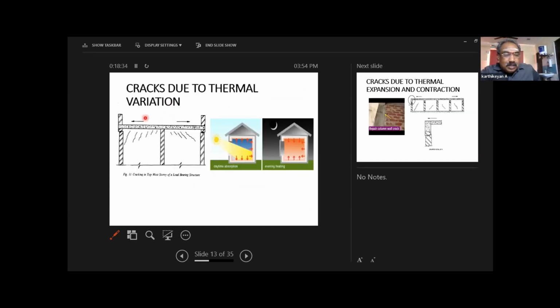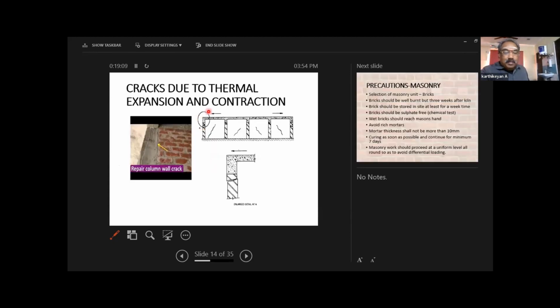Due to thermal variations, in our country, in Tamil Nadu, in South India, our temperature in summer is 45 degrees Celsius. In winter it is 20 or 25 degrees Celsius. So a 20-25 degrees Celsius variation is there. The top surface expands. When the top surface expands, there are cracks at the slab and wall junction. People may think if you provide a beam, there will again be less chance of cracks. Yes, if you provide a proper beam, there is less chance of cracks. But my next slide shows that even if you provide a beam, there is a chance of cracks below the beam. So how to avoid it?